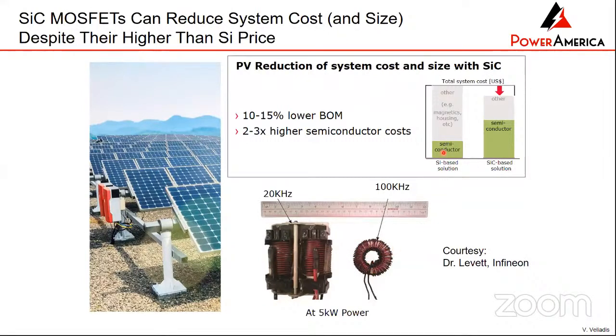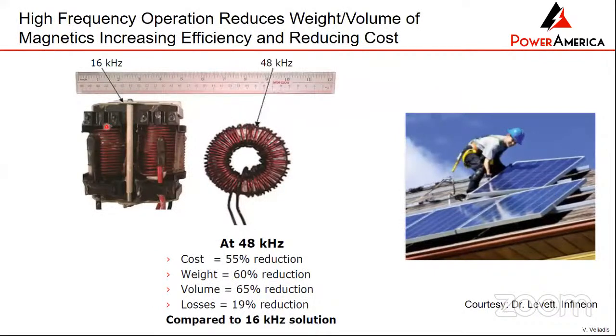So the bottom line is you're going to pay more money for the silicon carbide device, but because the silicon carbide device will bring a lot of simplification in the overall system, at the system level, it's already cheaper to use silicon carbide in several applications. And you can see this here one more time. When you're at the lower frequencies, your magnetics need to be very, very big. When you operate at very high frequencies where silicon is not capable of operating, then the magnetics become a lot smaller. So you have a reduction in cost, weight, volume, and of course, reduction in losses. You have a far more efficient system. And that's the selling point of silicon carbide. You have to look at the systems level when it comes to cost.